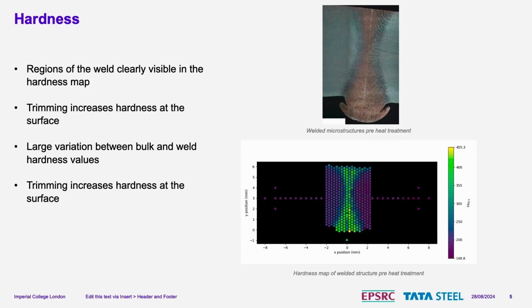And so when we take a hardness map of this, you can see quite clearly, you can just about see it on the edges here, these are our bulk material readings, which sit at around 150. And then within the welded region, we get to 450. So it's quite a stark difference. And you can just about see that we do get some differentiation between the regions of the weld. Another interesting thing to note is that when the bead is trimmed on the external surface, we seem to get some hardening effects at that point too.